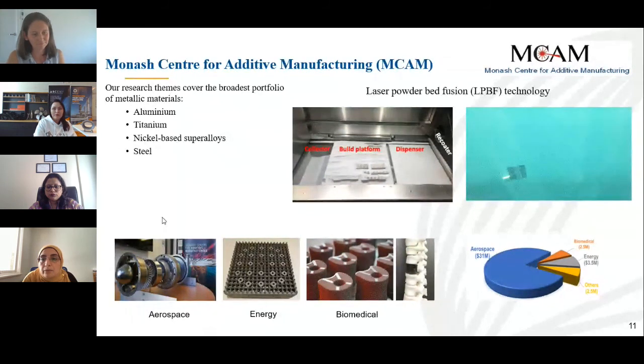So usually the first stage when we develop an alloy for additive manufacturing is process optimization. In simple words, we are trying to determine the set of processing parameters that we should use in order to achieve defect-free parts. And we use different techniques. We will not go into the details, but in one of the simple techniques, we build small cubes and then go for microstructure characterization in order to investigate the porosity level. Once we can achieve a density beyond 99.5%, then we can determine our processing window.